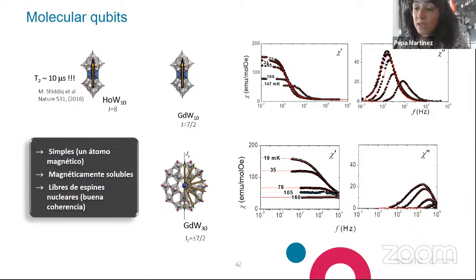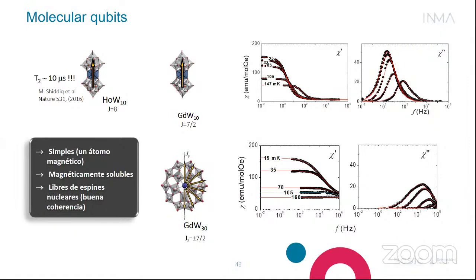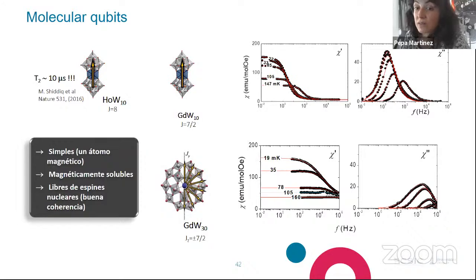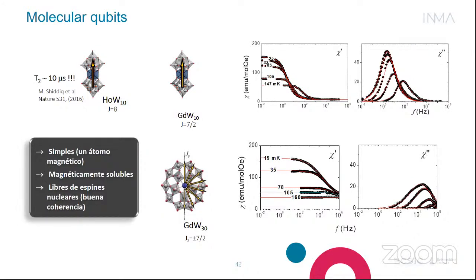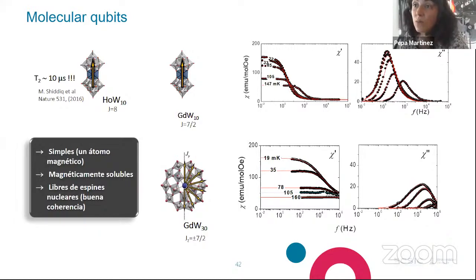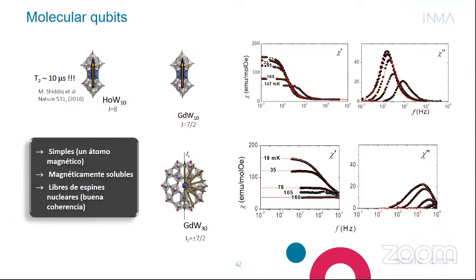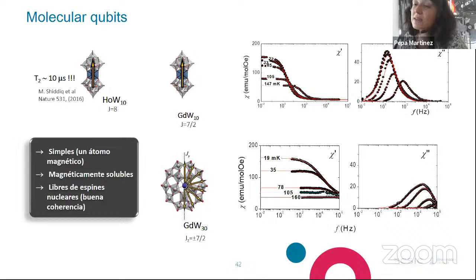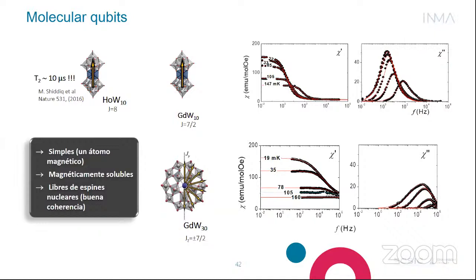You mean the sensitivity of the SQUID itself? Yeah, 1 micro-phi-naught per square root of hertz is quite a state-of-the-art value. 0.1. Okay, so that is the best you will get in the commercial or any conventional SQUIDs. 0.1 micro-phi-naught. Yeah, well, this is already a quite good SQUID, I would say. I believe you are saying your resolution is better than this, no? The noise we achieve at large frequencies is 50 nano-phi-naught per square root of hertz. 50 nano, right. So that is better than what is there in the conventional SQUIDs.